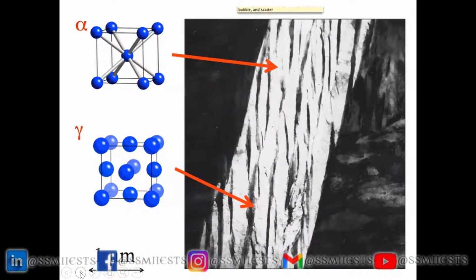And you've already seen that austenite does not have a ductile brittle transition temperature, so it's very good for toughness, whereas the very fine plates of bainite, which are a consequence of the mechanism of transformation, provide strength. And this particular microstructure, in which we have no carbides at all, because quite a lot of silicon has been added to the steel, and silicon retards the formation of cementite. This concept has found applications in a very large number of scenarios, and I will just mention 2 of them. But before I go on to mention the application, I want to show you a movie which explains why these plates are extremely thin. So if you go to the next slide.